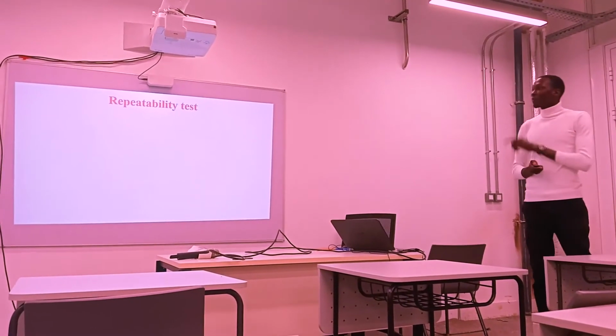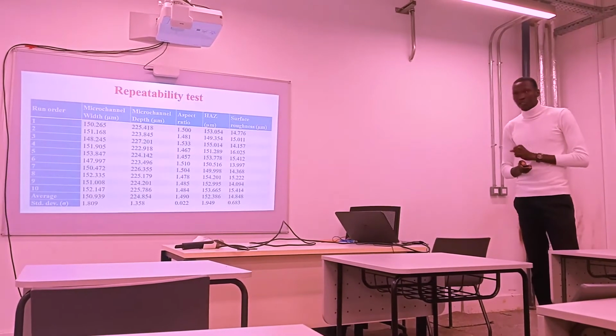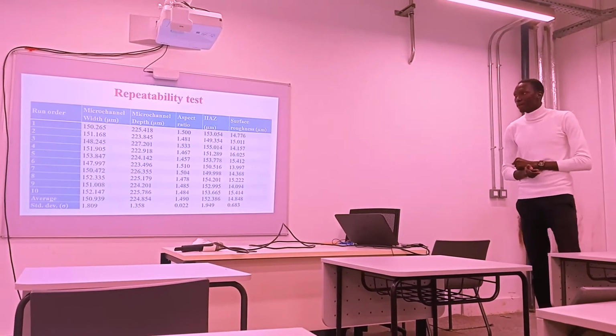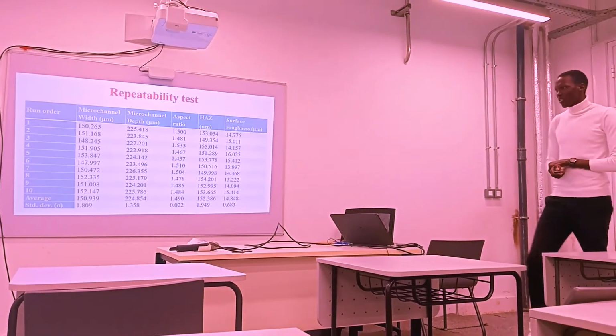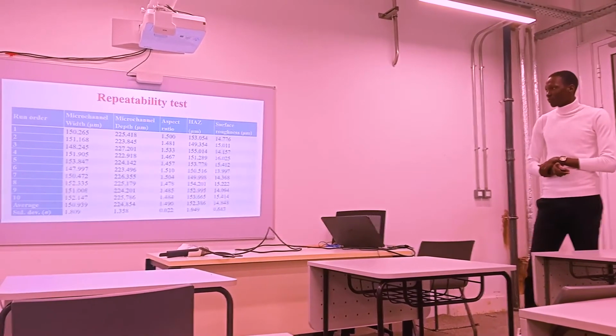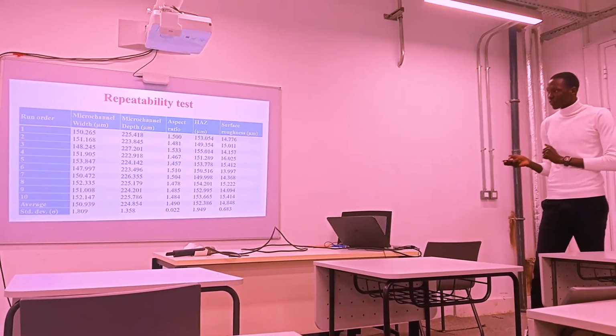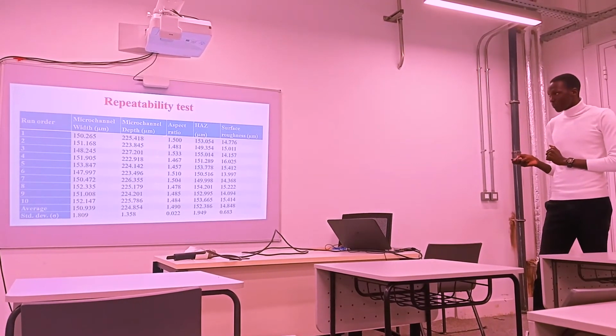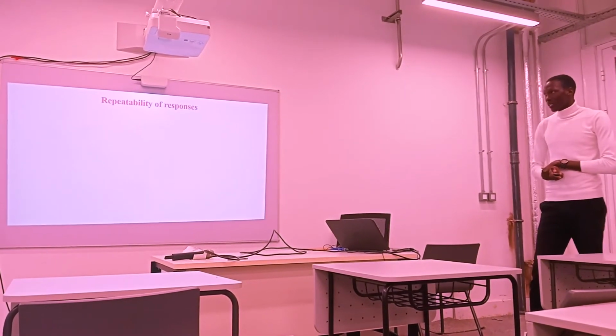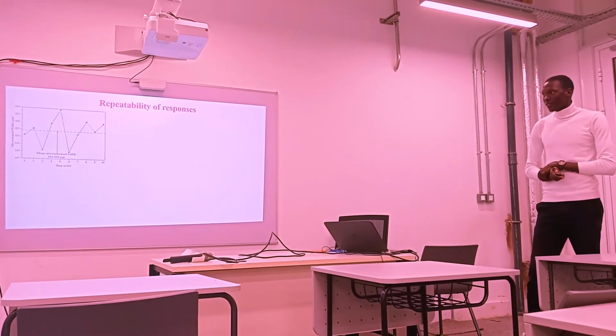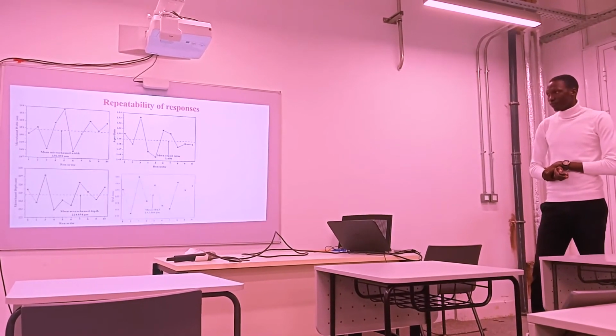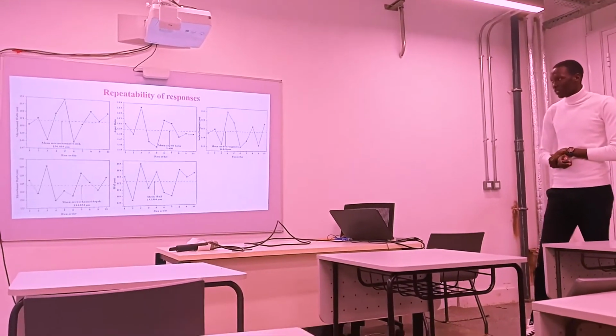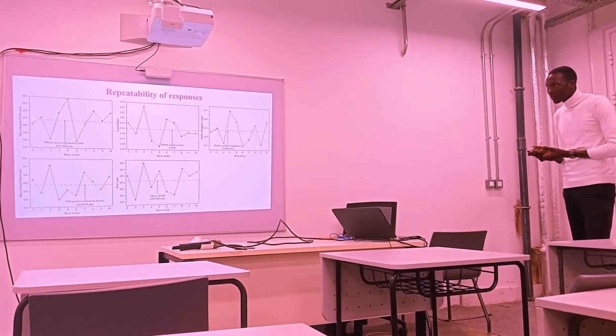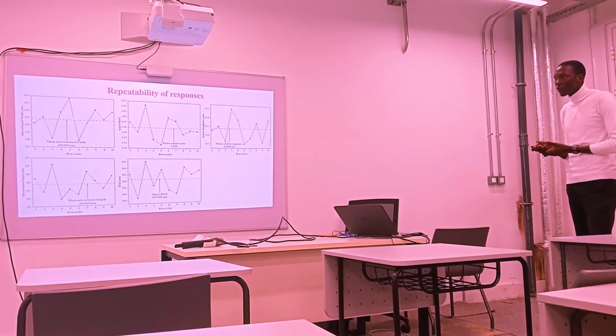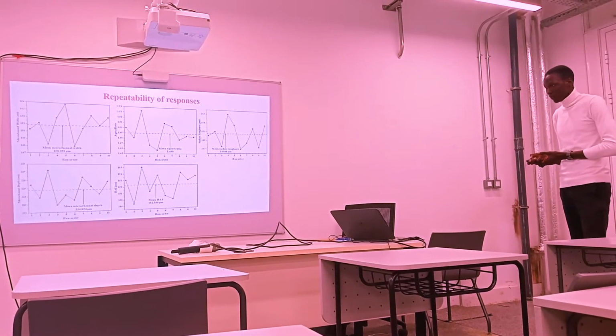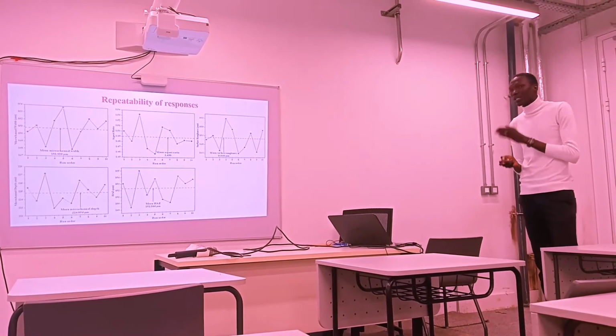Then we did a repeatability test to find out how repeatable the values were. We conducted 10 experiments under the same condition, the optimum condition, and then we got these values of the 5 responses. Then we plotted these figures to show the repeatability of the responses. Now this line represents the mean value. These lines are the mean values of the responses that we got from the 10 experiments.